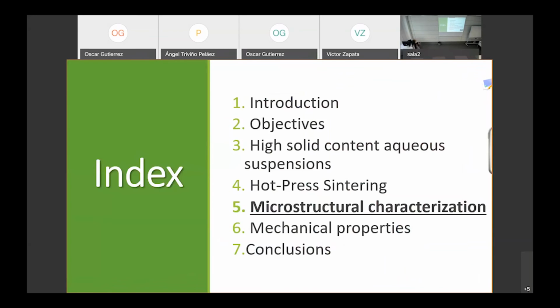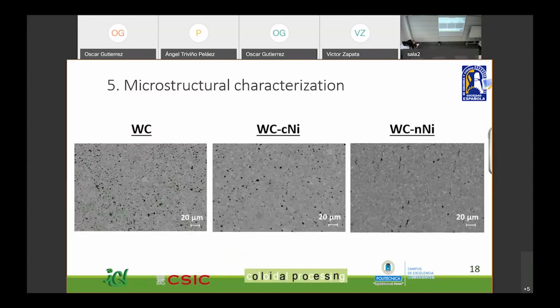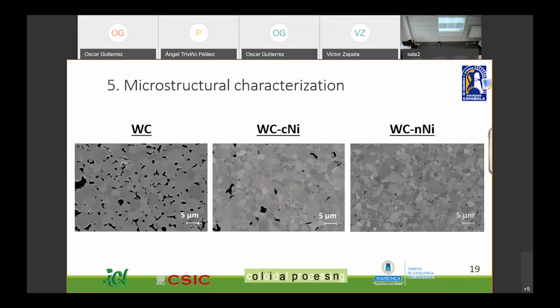So after that, we decided to carry out a microstructure characterization. So here I show you some polished cross-section surfaces of our samples. And as we could expect in the case of binderless tungsten carbide, and here maybe we can see it better in further magnifications, there is huge porosity present all over the microstructure. This is improving when nickel is present, especially in this case where porosity is not even noticeable.